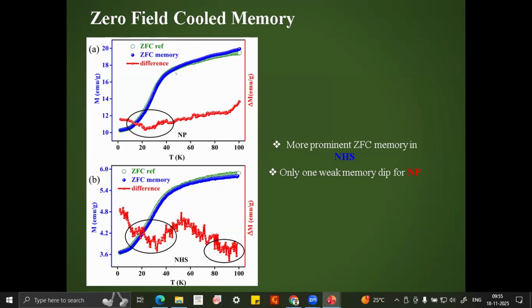Let me tell you this. There are several papers saying that if your system shows the zero field cool memory, then only it is a spin glass relaxation. On the other hand, if your system is a superparamagnetic system, then it cannot show zero field cool memory. In the earlier days, around 2000, people were confused about how to distinguish between superparamagnet and spin glass, because both show slow spin dynamics. But the zero field cool memory effect is the one that conclusively says that its presence indicates spin glass nature, while its absence can indicate superparamagnetic nature.